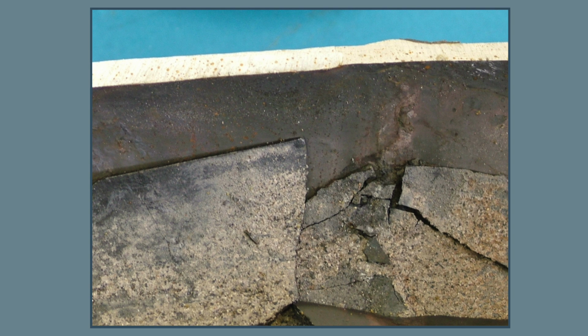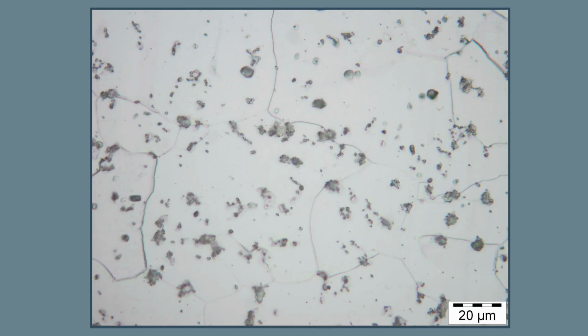When you look at the metallurgy of this, now carbon steel is usually made of ferrite pearlite microstructure. And here, when we did a cross-section, we could see that a lot of the pearlite had spheroidized. Normally they are lamellar, and here we can see that they are nodular. So we could see that damage within the metallurgy of the steel. So we knew that the tube had run hot. We had this excessive deposit.